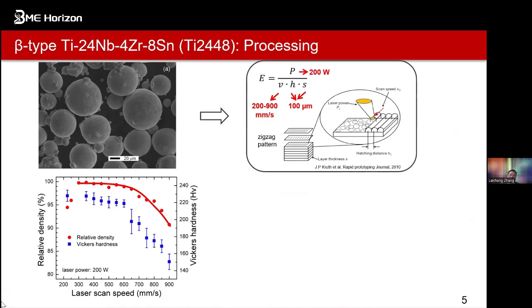For example, if we get the structures with lower density, the strength will not be good enough. And of course, that's what causes premature fracture. That's why for most of the structures we try to make the solid part more than 99%. So we get this information with the different parameters. We can see this with the laser kept at 200 watts, and then reducing the scan speed, we can enhance the relative density, going to 99% of titanium.